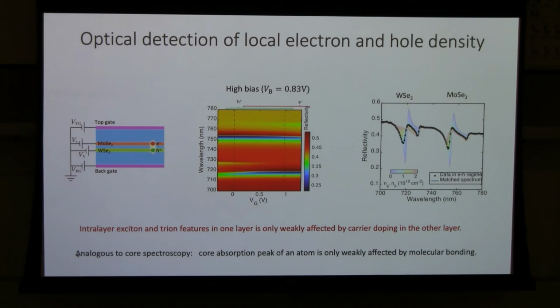If we do a line cut, we can plot the optical spectrum. That is the black curve. On top of that, we can superpose the absorption spectrum of the WSe2 layer when it is only hole doped, and the MoSe2 layer when it is only electron doped, which is the colored plot. It turns out we can match this co-doped region almost perfectly to a specific spectrum when it is only electron doped or only hole doped.